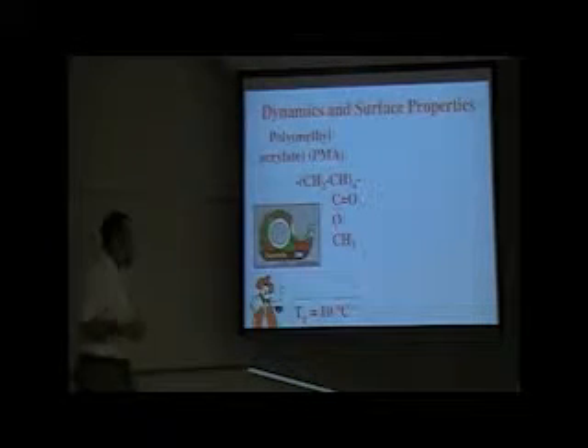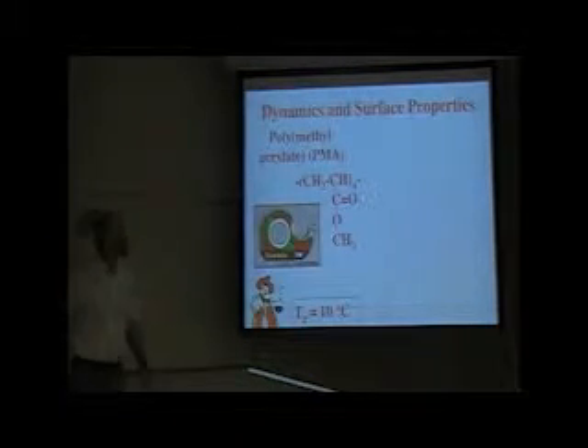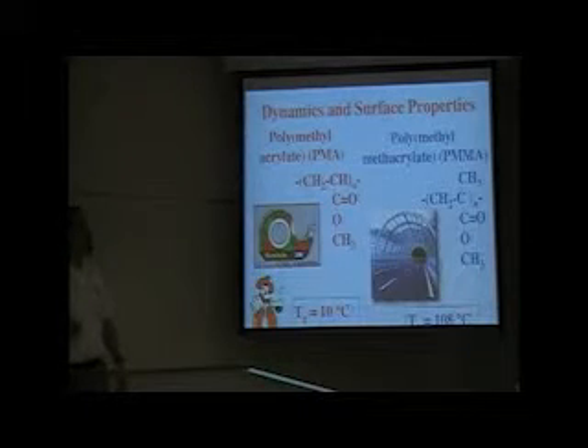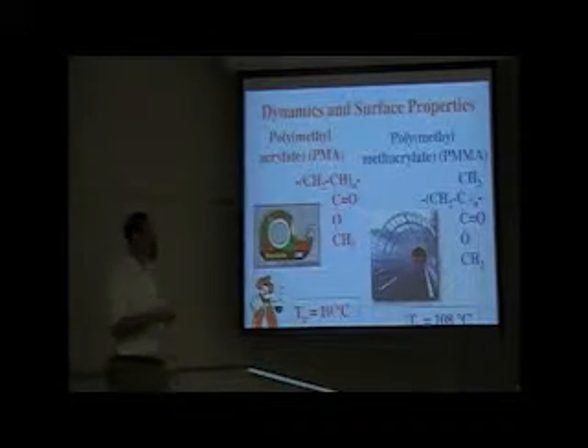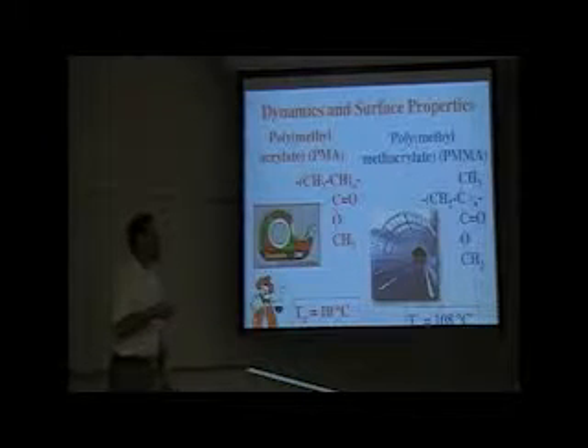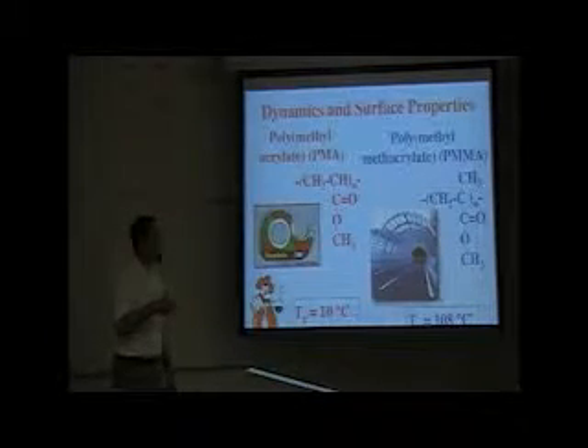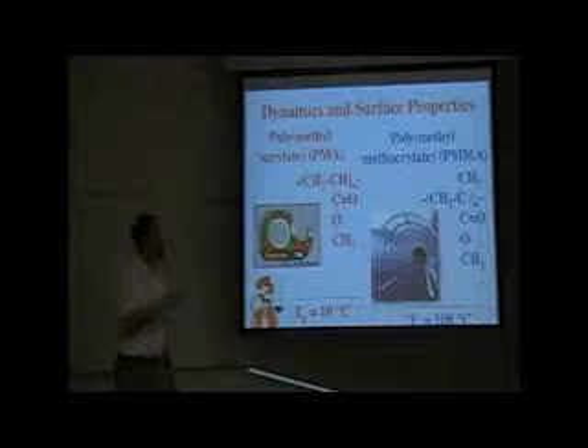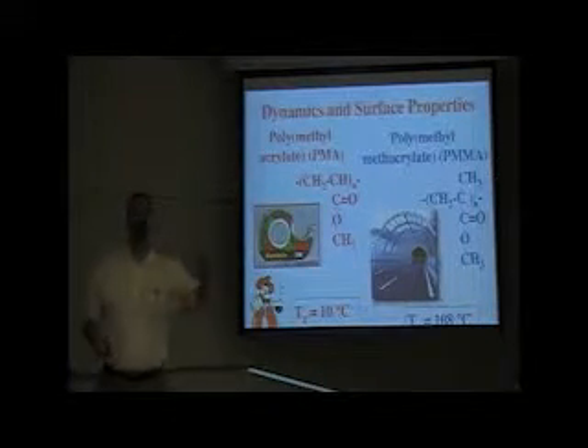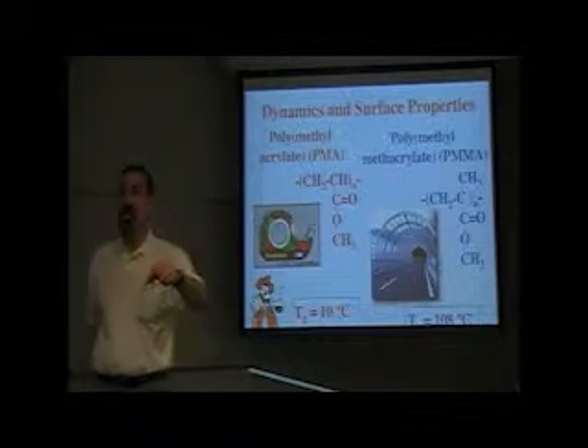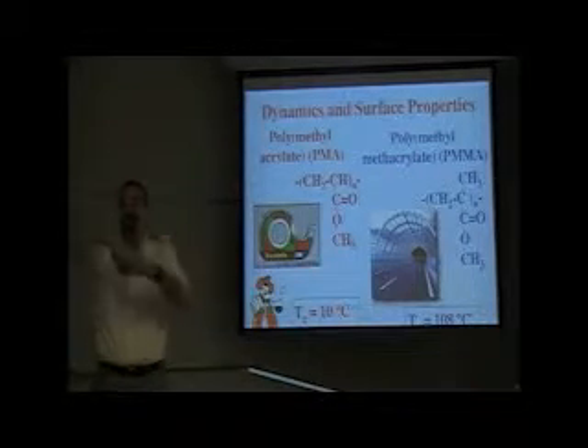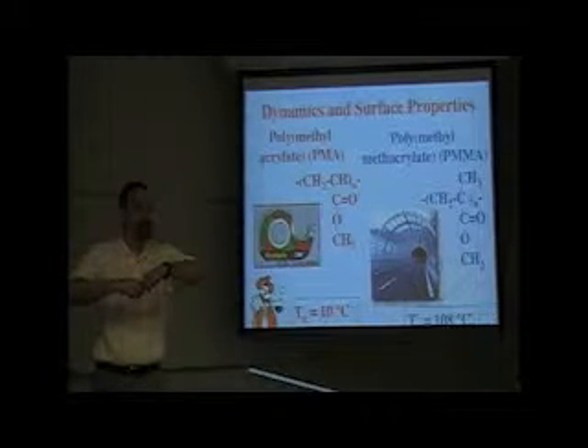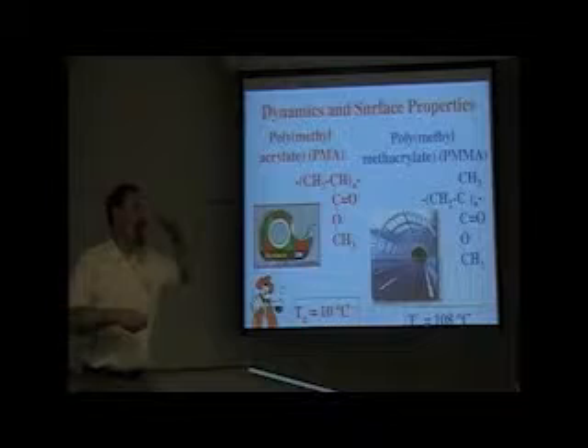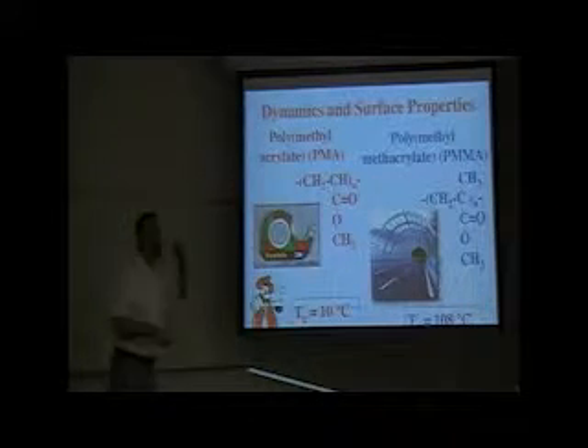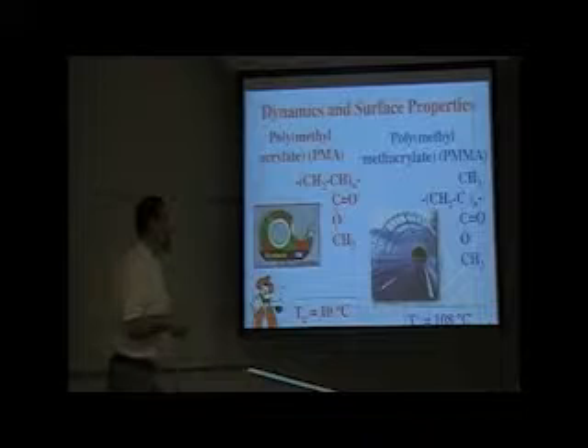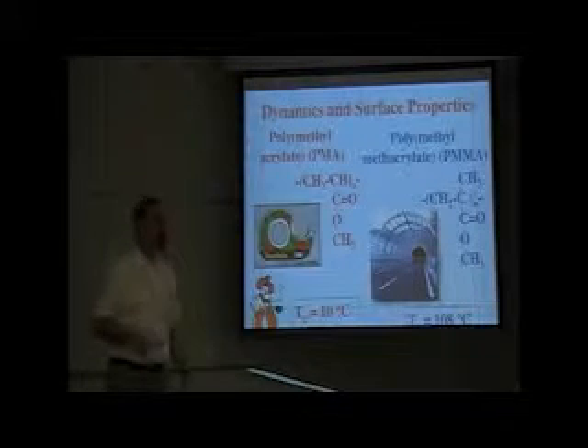So a related polymer is polymethyl methacrylate. This is plexiglass. Here's a plexiglass enclosure on a road. But notice the structure is almost the same. It's still a polymer, but it's just got this methyl group instead of the hydrogen group. Just that methyl group alone is enough, because of steric hindrance, to cause the polymer chains to not be able to wiggle as much, because the methyl group gets in the way. And now the glass transition temperature on this material is 108 degrees. It's almost 100 degrees higher because of this methyl group.